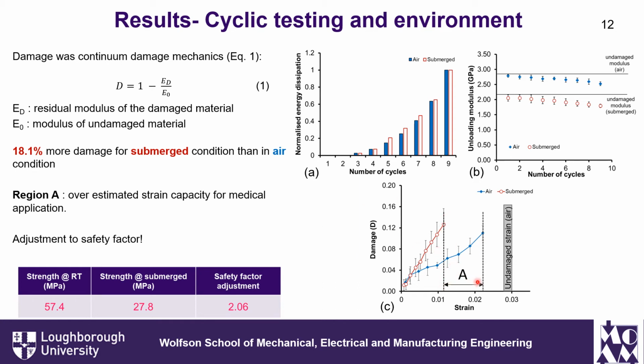Other than that, we also identified a region of overestimation of strain capacity for medical devices. And because of all these differences between these two testing environments, we decided to introduce new safety factor for designing medical implants. So we took the strength at room temperature and then compared against the strength at submerged testing. And then the adjustment was basically multiplying by 2. So we advise future study to use this new safety factor for designing medical implants of biodegradable polymers.